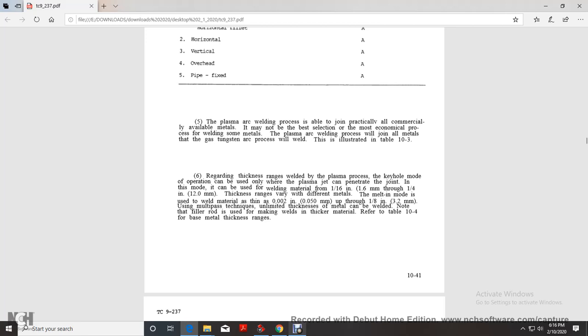Regarding the thickness range of the plasma process, the keyhole mode of operation can be used with the plasma joint. The jet can penetrate the joint, and this mode can be used for welding metal material up to 1/16 of an inch. Thickness ranges vary with the different metals. The melt-in mode can be used for welding material from 0.002 of an inch thin up to 1/8 of an inch. Using multiple pass techniques, unlimited thickness of metal can be welded.